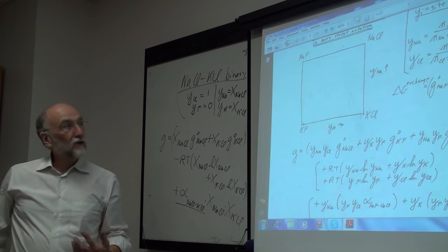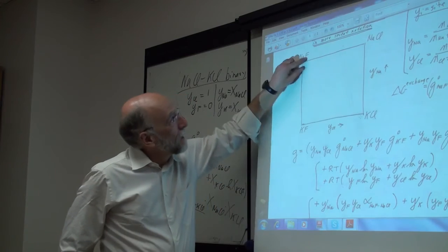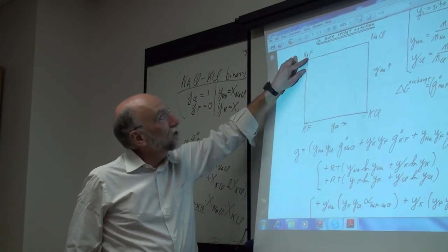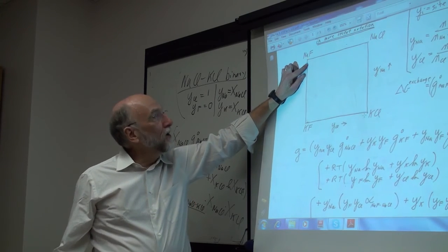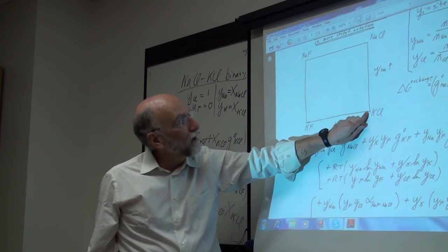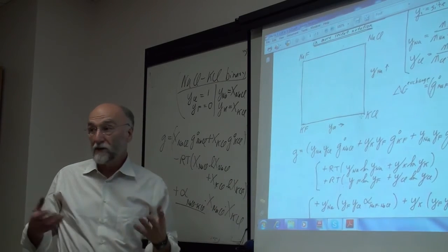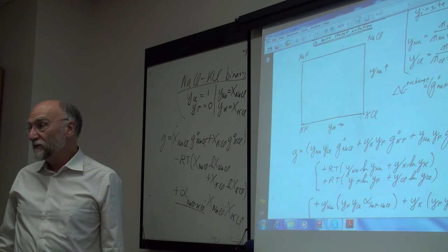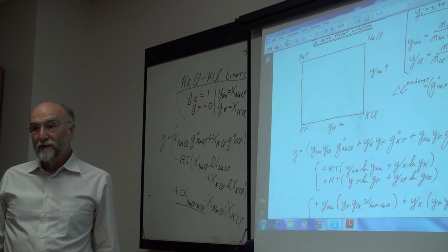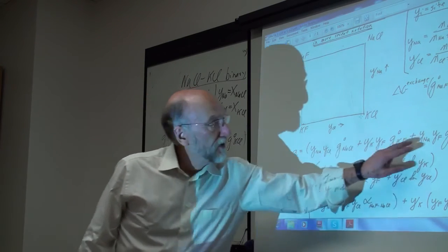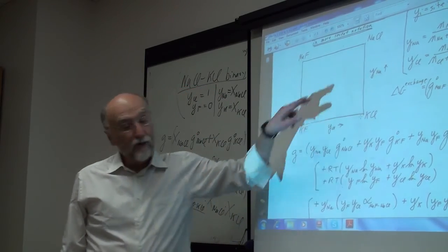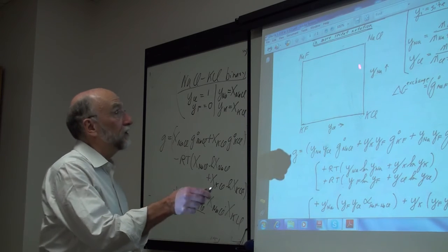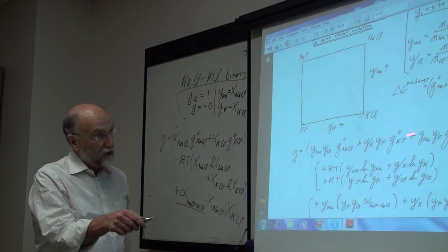Okay. So if I mix any binary salt, if I just take a binary phase diagram, binary enthalpies of mixing, I do the optimization, the only information I'm getting from my binary optimizations is what happens when second nearest neighbors change. I'm not getting any information on what happens when you change the number of first nearest neighbors, which is the most important term. And that's tied up with these. So just your binary optimizations don't allow you to make this approximation. The most important terms in this whole model are these G naught terms here.